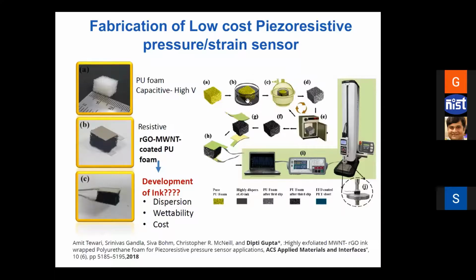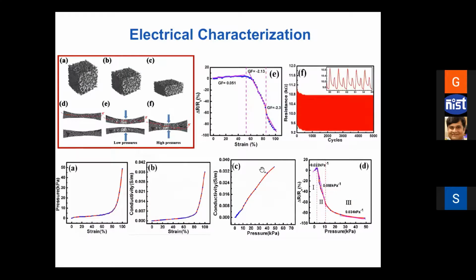So you take a foam, dip it in this ink, dry it, put electrodes, and then you test it. Electromechanical testings are done: you put your sample over here, apply pressure and measure its electrical characteristics. And these are different characteristics showing that when you apply pressure, all these components start coming together and the resistance decreases. We tested it very rigorously with respect to resistance change with pressure strain, conductivity versus pressure, resistivity versus pressure. Lots of data we had collected. We also checked different cycles, how it behaves, which speaks to its durability.